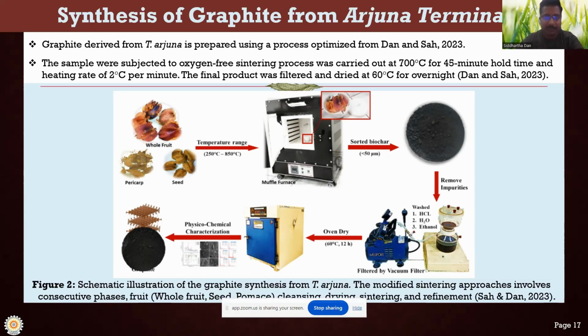And you can see that this is the production pathway of synthesis of graphite. After that, we tried various temperatures, from 250 degrees Celsius to 850 degrees Celsius. But we found that only at 700 degrees Celsius, after 45 minutes of sintering the whole fruit of the Arjuna terminalia, can we find the graphite. The final product was filtered and dried at 60 degrees Celsius overnight, and we can find the pure graphite sample, which eliminates all the impurities and all the polyphenol or glucose monomers.